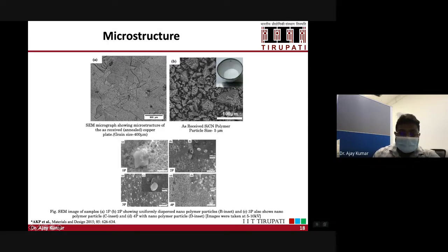So when you take the microstructure of these composite materials, these are the scanning electron microscope pictures, micrographs. You need to be very careful while taking these pictures because they are all polymer particles. So you need to control the voltage or power of the system. Otherwise, these polymer particles can burn, and then you may not be able to see those particles inside the matrix. So we fix our voltage around 5 to 10 kilovolt while taking these pictures from SEM.